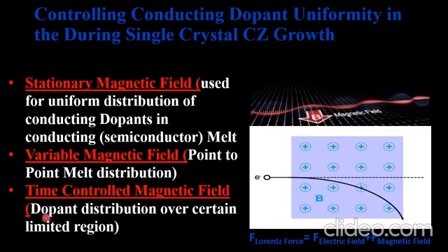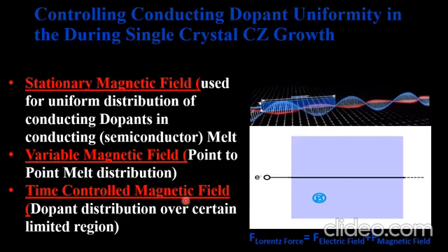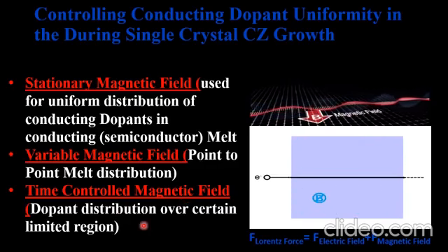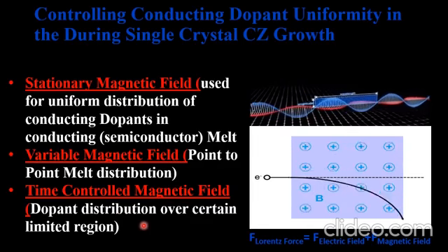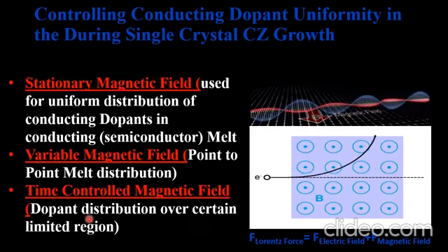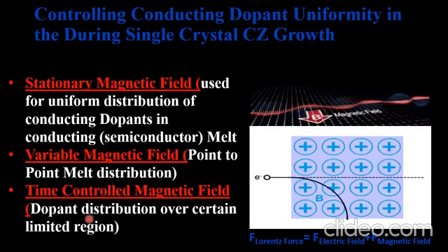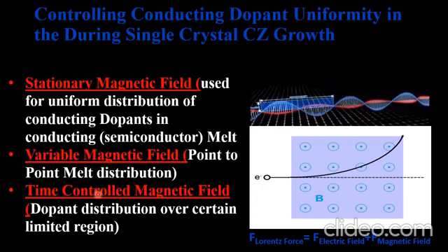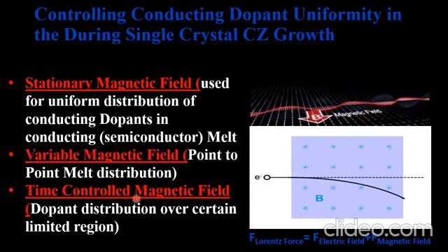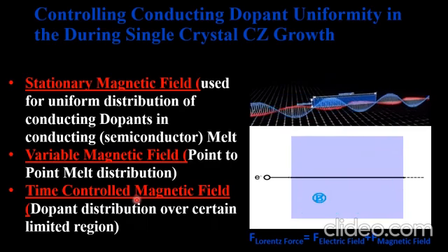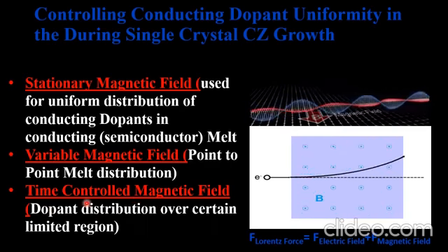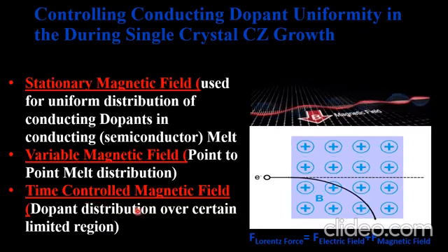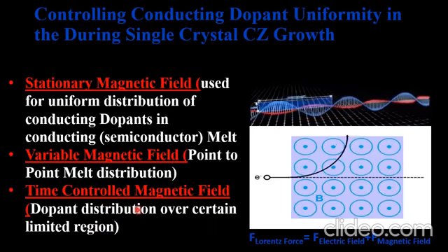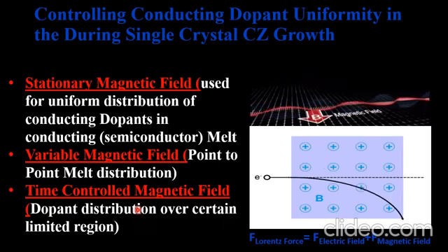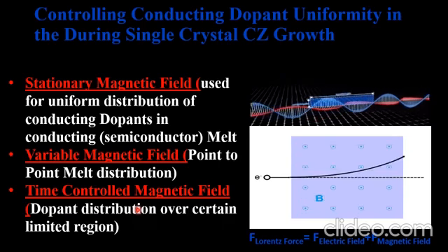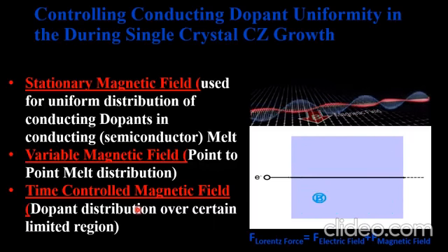The industrialists use a time-controlled magnetic field. So let's say the pulling rate of the single crystal is 1 millimeter per minute, and the industrialists want the dopant distribution up to 1 millimeter. So they set a magnetic field for 1 minute, and in this 1 minute only 1 millimeter of the single crystal has a dopant with a certain distribution, and when this magnetic field is shut off, there will be no dopant concentration in the single crystal. So dear students, the magnetic field plays a very important role in distributing dopant inside the semiconducting single crystal.